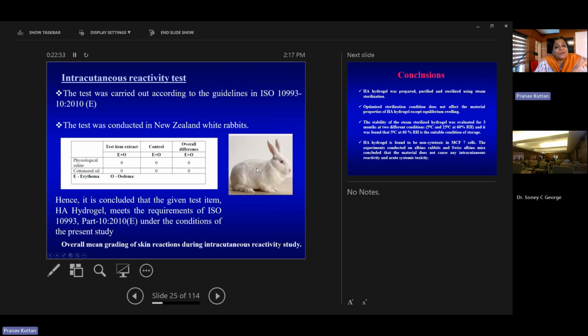Then the intracutaneous reactivity test was done in white rabbits. From this hydrogel, two types of extracts will be taken. One is the saline, that is the water-based one, and another one is cottonseed oil. Both these extracts will be taken and given as an injection to the rabbit. And that knee part will be examined for any irritation. It was found that there was no irritation, there was no swelling, and some amount of sample will be taken from that knee and histopathology will be checked. And it was found that there was no change. So this test also passed.